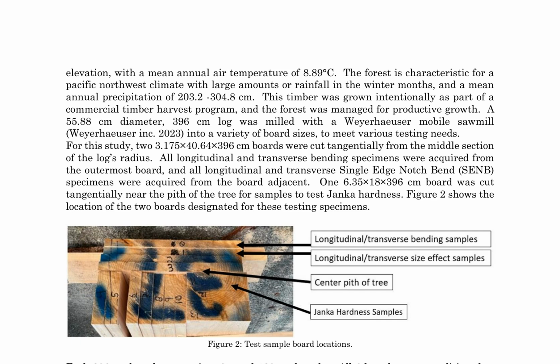For longitudinal and transverse bending specimens, as well as single-edge notch bend (SENB) specimens, 3.175 x 40.64 x 396 cm boards were cut tangentially from the middle section of the log's radius. A 6.35 x 18 x 396 cm board was also cut near the pith for Janka hardness samples. Each 396 cm board was divided into 3 equal 132 cm lengths and conditioned at approximately 21.11 degrees Celsius and 65% relative humidity for 2 weeks.